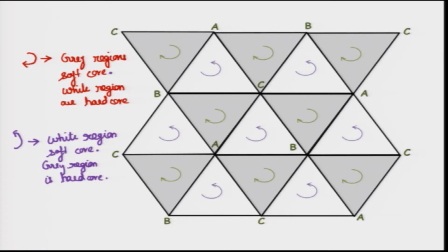Now, when we are looking at it, like I said, we are looking in the 1-1-1 direction, and over here this is your bar 2-1-1 direction, meaning these planes are your 2-1-1, 1-1-2 type of planes, and this is your 0-1 bar 1 direction. So, the planes should be oriented like this, and there are 3 possible planes. So, if we talk about this one,